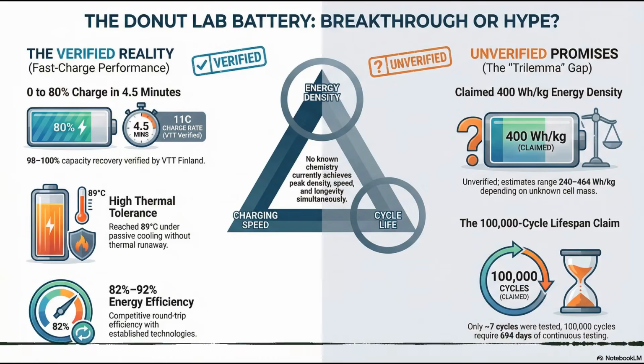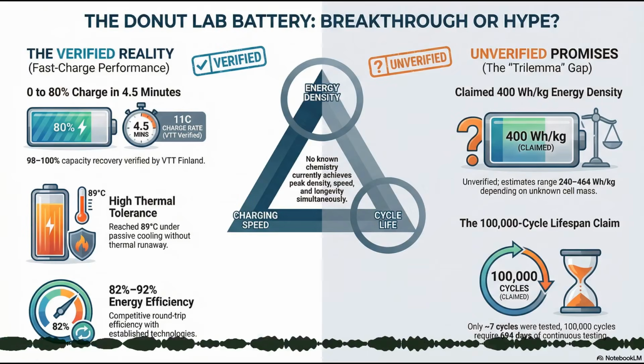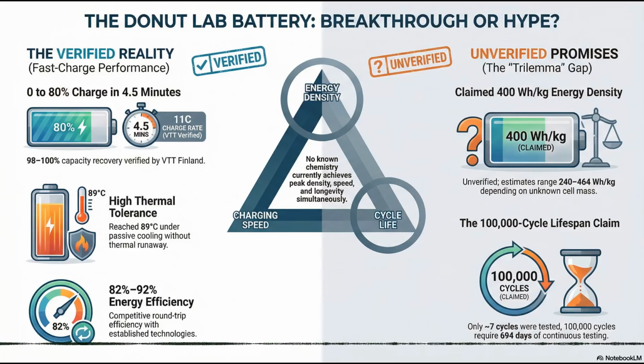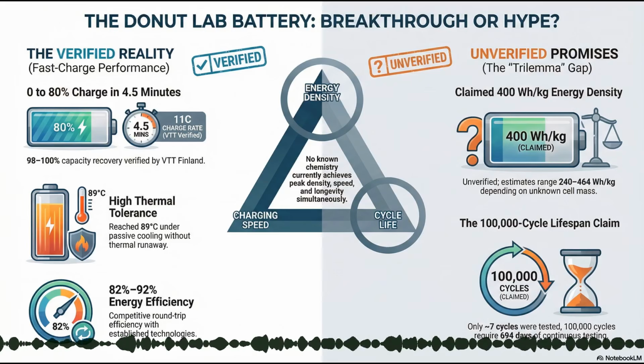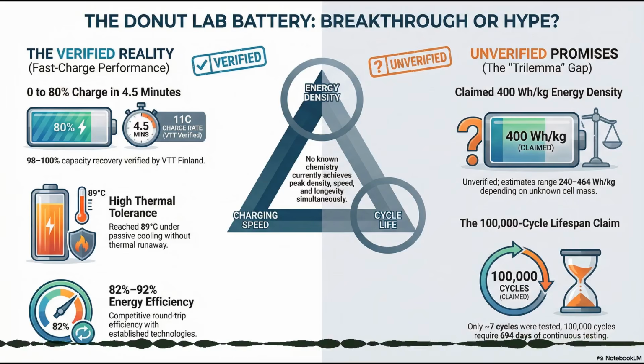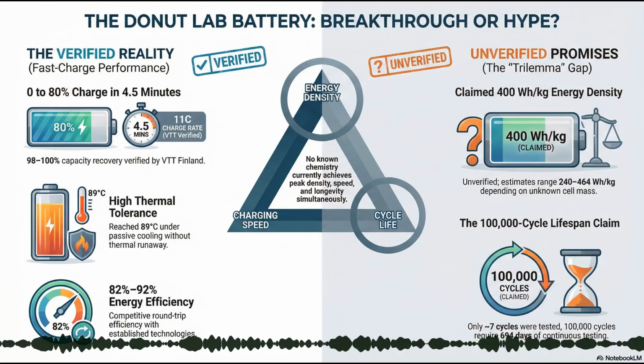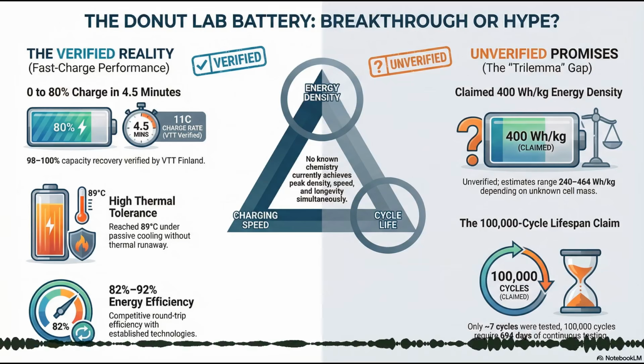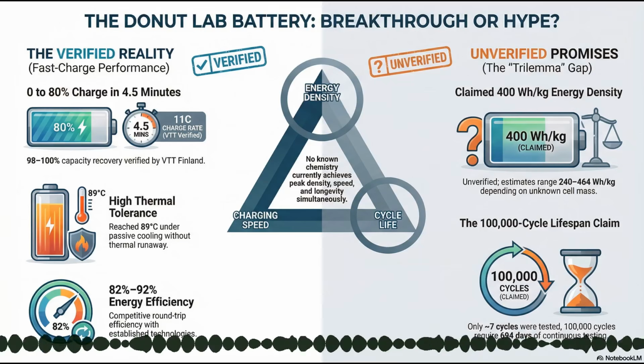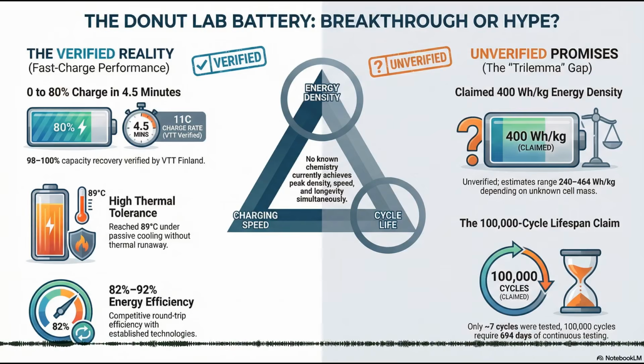It's mostly mechanical. Volume expansion. When you charge a battery, you are literally shoving physical lithium ions into the anode matrix. It takes up space. Yes. If your anode is silicon, it expands by up to 300%. Even graphite expands by about 10%. And if it's a lithium metal anode, which you generally need to hit 400 Wh/kg, you're actually plating metal, growing a physical layer of lithium, and then stripping it away. That expansion and contraction is like the cell is breathing. And solid materials don't like to breathe.